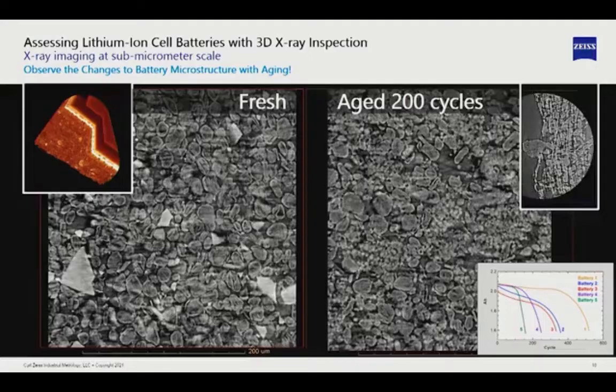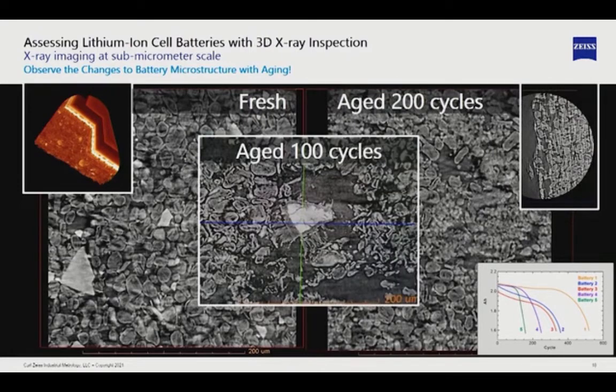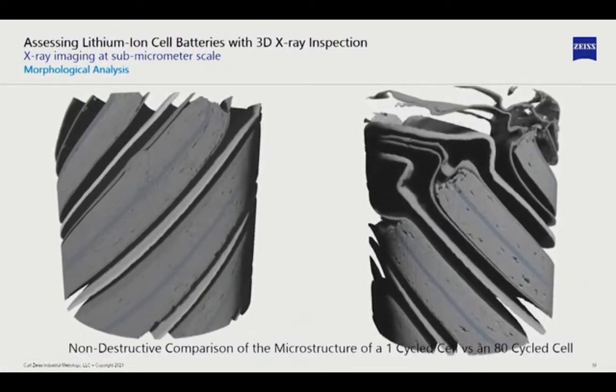And for batteries, aging studies are very important as well. So we did studies, for example, with a fresh battery and then a battery cycled 200 times. And you can see that the silicon has almost disappeared from the structure. We were also wondering what happened in some of the regions after 100 cycles. And you can see that there was a cracked particle there that pushed away the other particles around it. That was really an interesting detail.